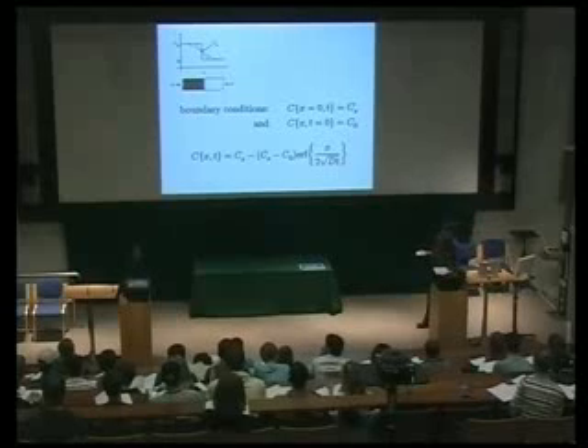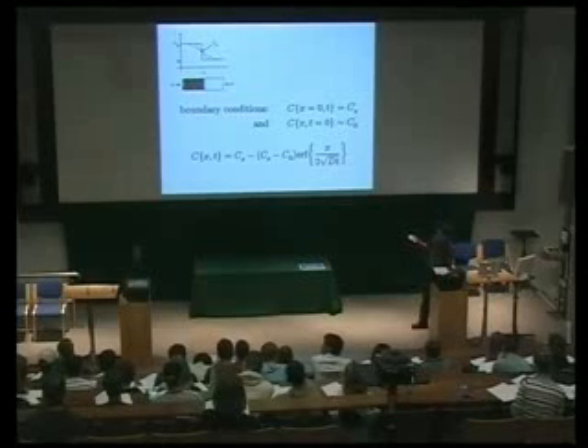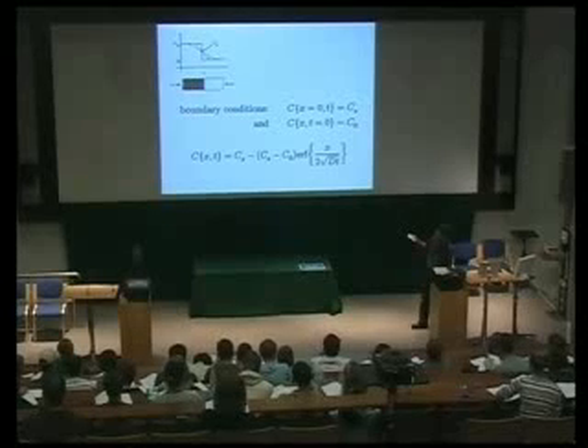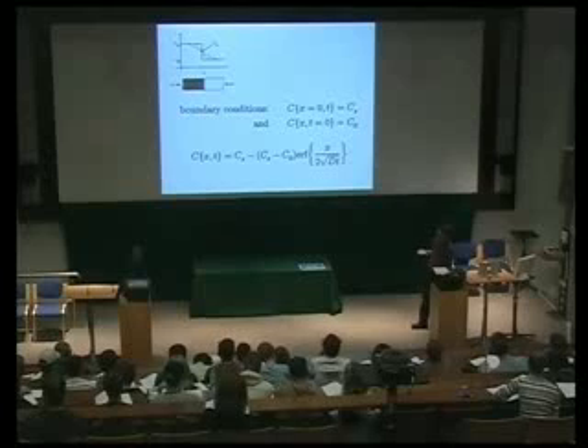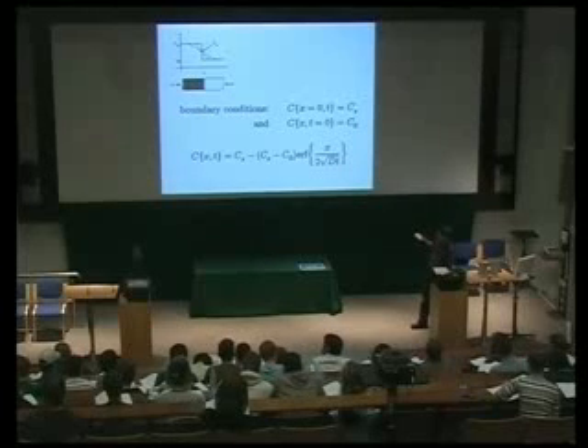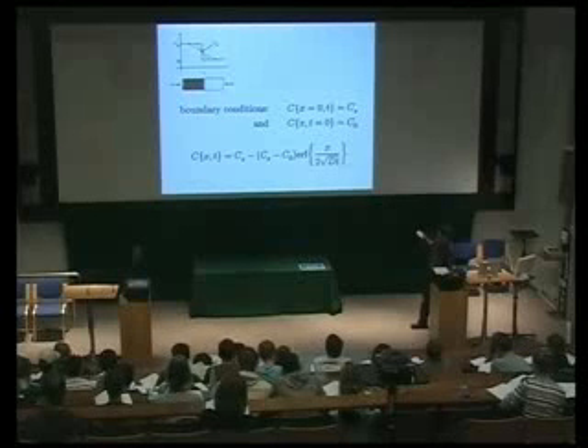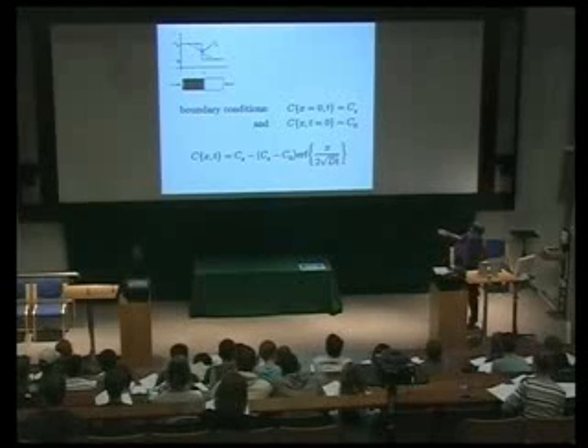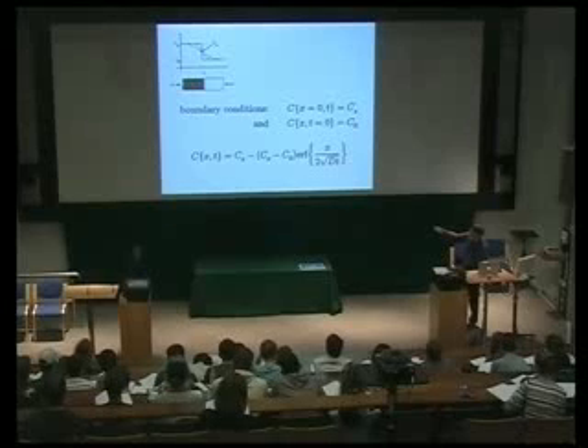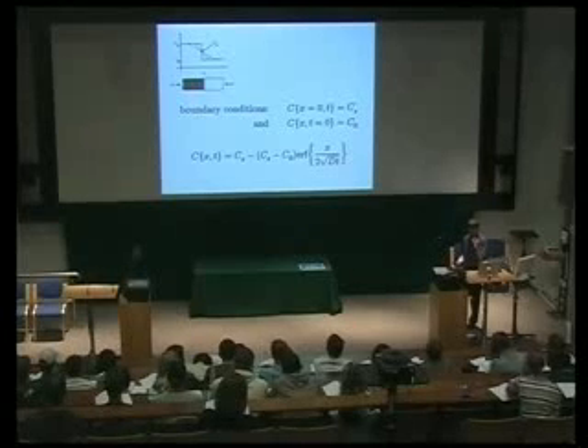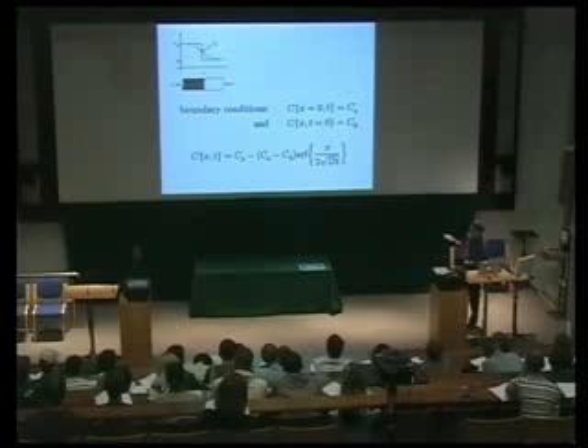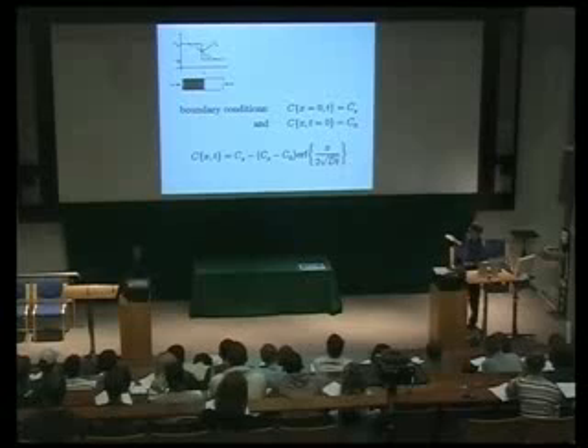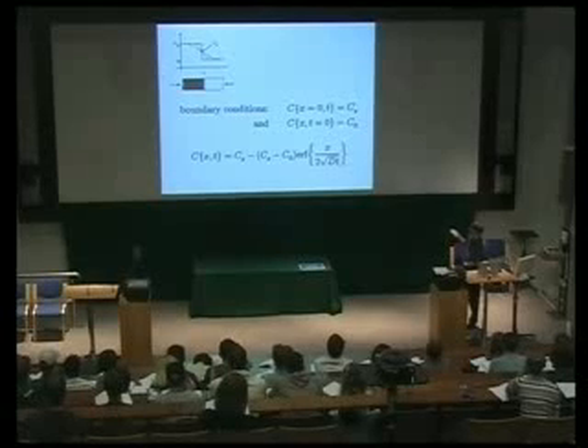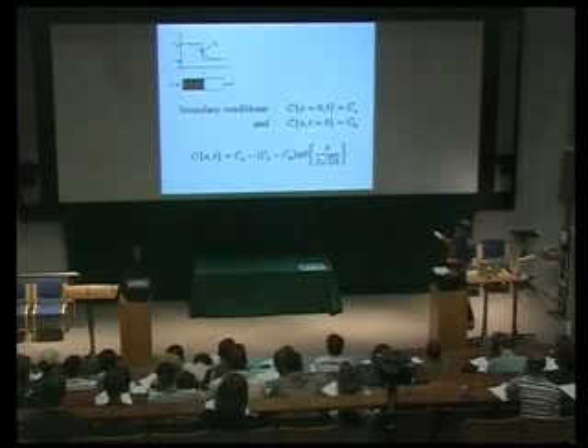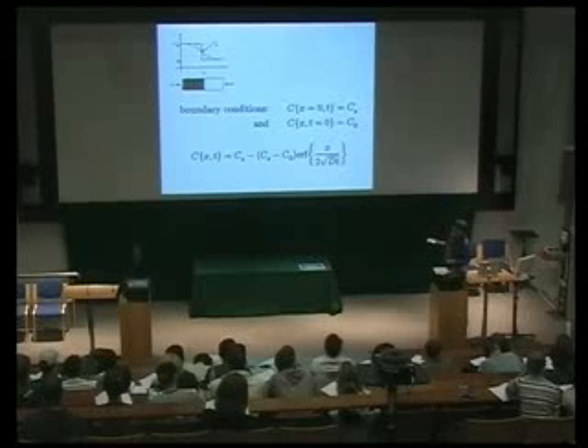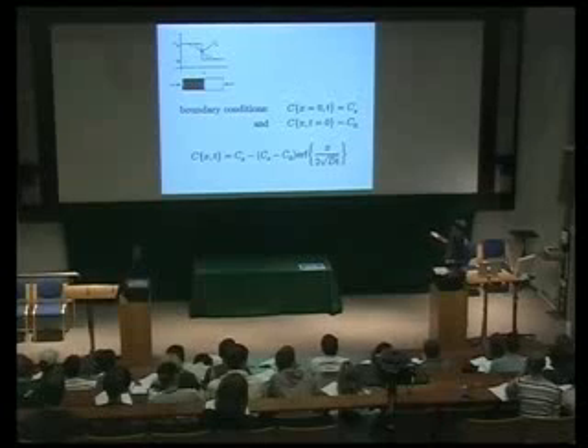And of course, the boundary conditions for this. Basically, supposing you start off as a step function with no diffusion at all, then the concentration when x is 0, at any time, will be Cs, because that point remains fixed. We've got equal fluxes going, and therefore the concentration in the middle doesn't change, and the concentration far away will be this value C naught. So when we put those boundary conditions, we get the variation in concentration here as an error function.